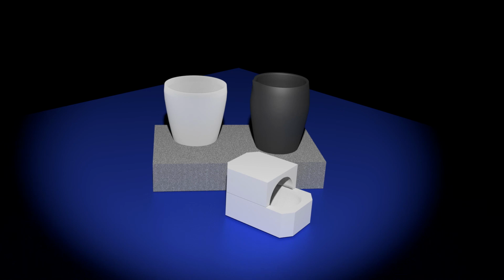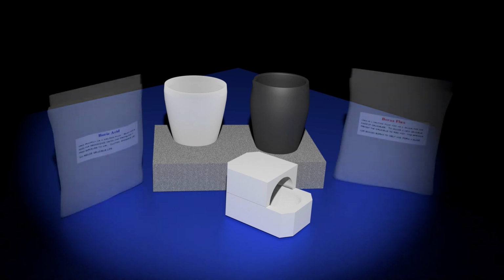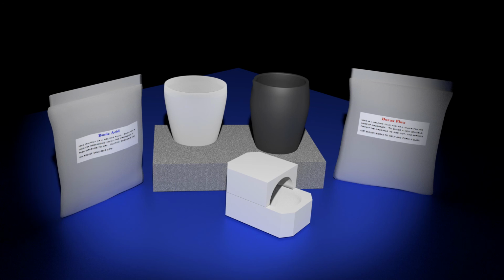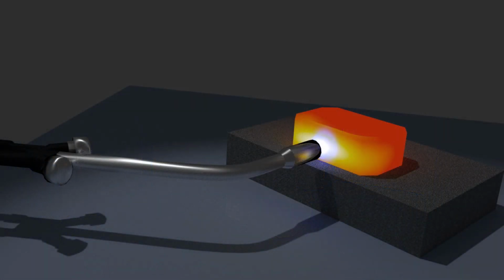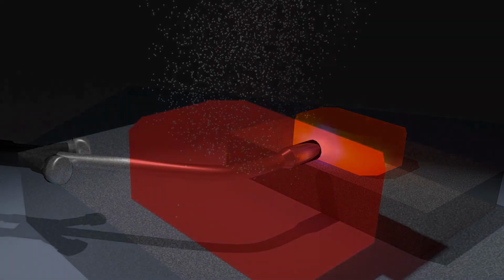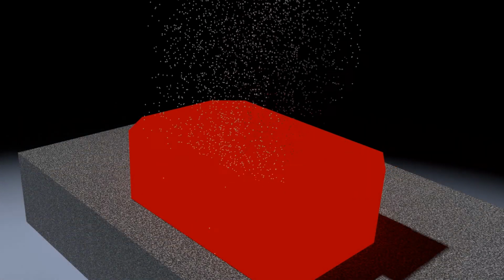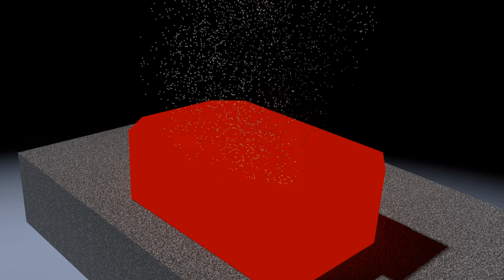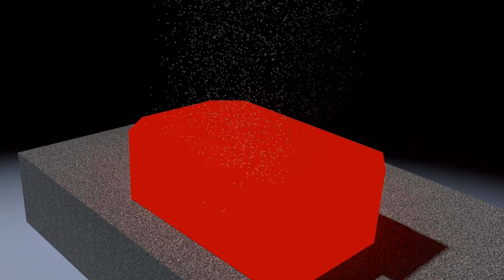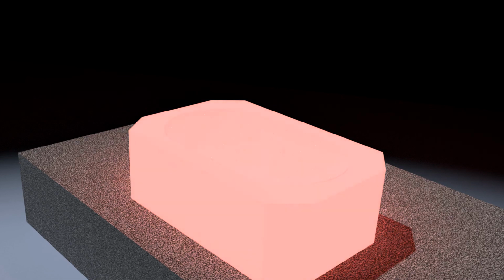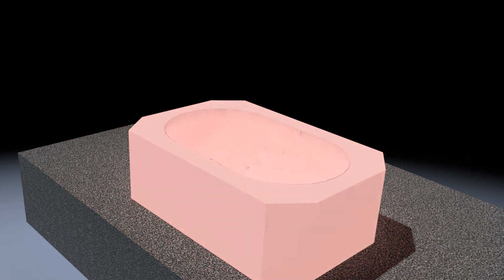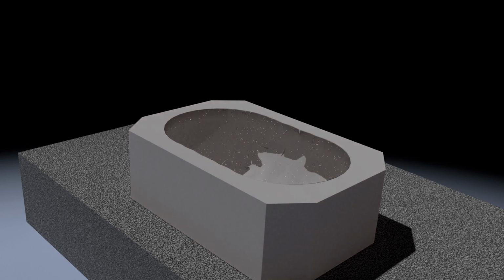Preparing your crucible. Select either an unused crucible, or one that has only been used to melt refined gold. When using a fresh crucible, you must first flux it, sealing its pores, thus preventing it from absorbing gold. Heat your crucible to red hot. Sprinkle flux on the inside of the crucible. A mixture of 50% borax and 50% boric acid is the most commonly used flux. The flux will melt rapidly, forming a thin glaze and sealing the crucible's pores.